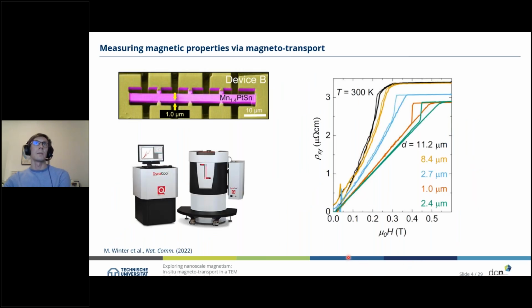So how are magnetic properties measured via magneto-transport? Normally you have a device like a cryostat, a PPMS, and you shape your sample so that you have contacts on it where you run a current through and measure voltages. What was found for such materials, for example from one of my colleagues, is that if you measure the Hall resistivity for different sample thicknesses, the magnetic properties which you measure by that curve, the Hall resistivity as a function of magnetic field, depend dramatically on the thickness of your material. So there are different contributions to those measurements which you cannot directly see from simply measuring magneto-transport in such a device.